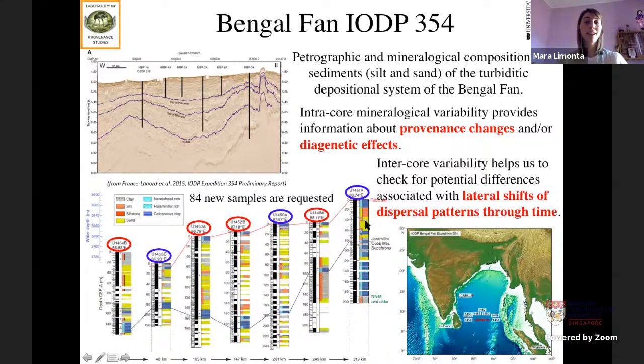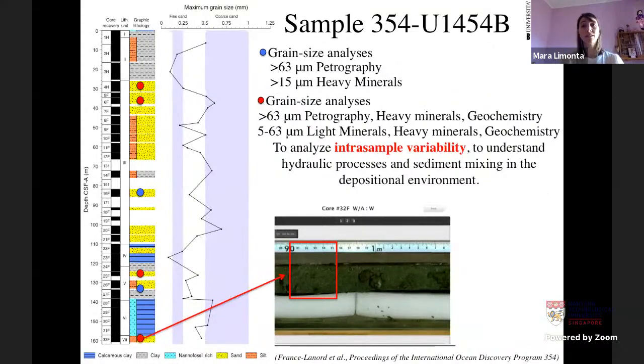So what we want to analyze is the intracore mineralogical variability to have information on the provenance change and diagenetic effect. And we want to analyze also intercore variability to check if we can see the lateral shift of dispersal pattern through time. I will show you the first data and the analysis that we want to do in the first core. Here is 1454B. In the blue samples, we want to analyze petrographic composition in the fraction bigger than 63 and heavy minerals in the fraction bigger than 15 microns.